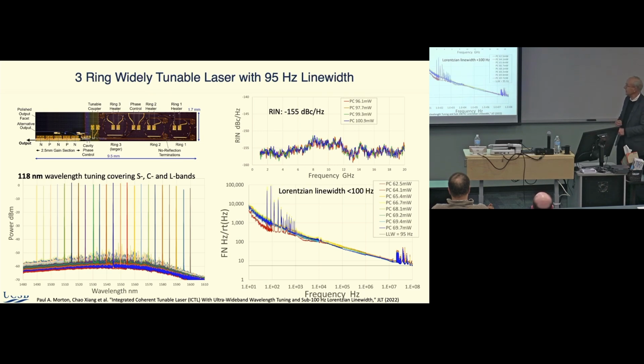It's maybe 2 millimeters by almost a centimeter. That's a fairly big die. But now you can tune over almost 120 nanometers. That's a lot for one gain region. It has low RIN and fairly low line widths, about 95 hertz for near-in line width. So again, I'm talking about the high frequency line width out here at higher frequencies.